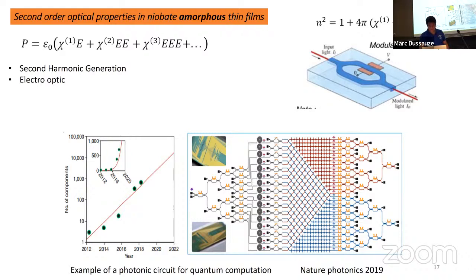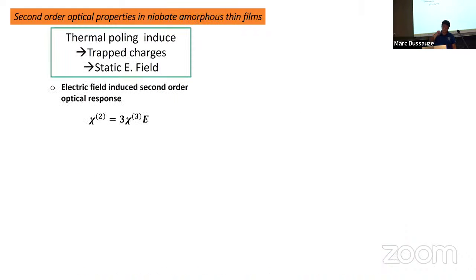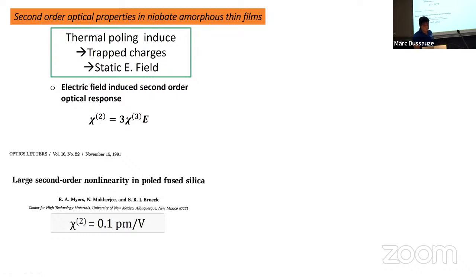All right, so how can we put nonlinear response in a glass? We put in this electric field, as I told you, because my static electric field can interact with the Chi3 to give me a Chi2 and some response inside the glass. This was discovered in 91, so that's a very old story. In 91, they found 0.1 picometers per volt in silica. But we wanted to compete with the very classical crystal lithium niobate, which is 60 picometers per volt. So you see there is more than 2 orders of magnitude of difference.